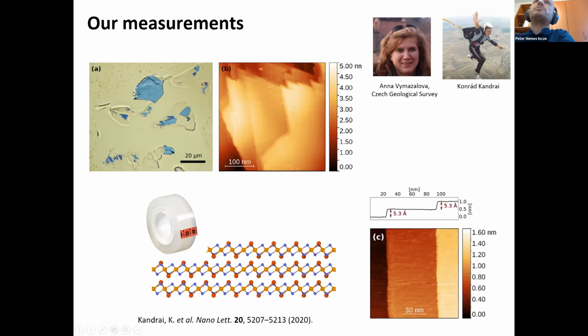Here you can see some crystals of the material on this gold 111 surface. If you take a low magnification STM image, you can see steps on the surface that are very similar to what you would expect for a Van der Waals layered material. You can also maybe see that most of the steps have around 30 degree angles. This is very indicative that the cleavage plane within the layer is along some crystallographic directions, which turned out to be the zigzag directions.